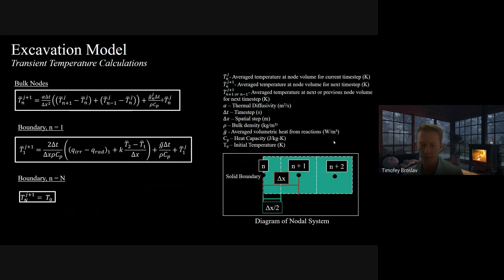First, after the initial setup of conditions and material properties, the temperature solution was solved at each time step, and this is using Euler's method. It's a finite difference method with some slight adjustments to include for chemical reactions. The top is the equation that was solved for the bulk nodes, so within the material. The middle equation is what was used to solve at the surface boundary that was impinged by the light beam. And lastly, there was a constant temperature condition for the innermost node. It is assumed that within the spallation time, the heat did not penetrate that far into the material. It was sufficiently far away to basically be infinitely far.